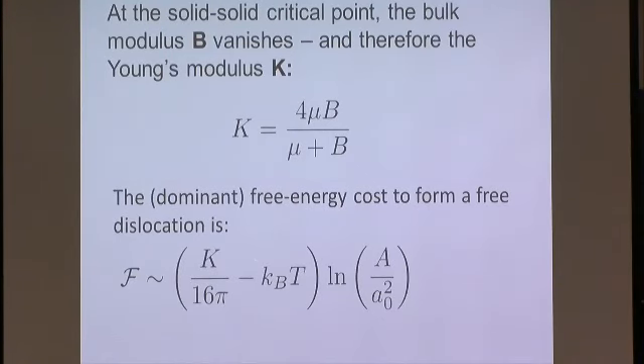So at the point where k over 16 pi is equal to kT, you have a transition where spontaneously dislocations will form. Now this argument is highly oversimplified, but mysteriously, in the end, that final conclusion about the value of the Young's modulus is still correct.